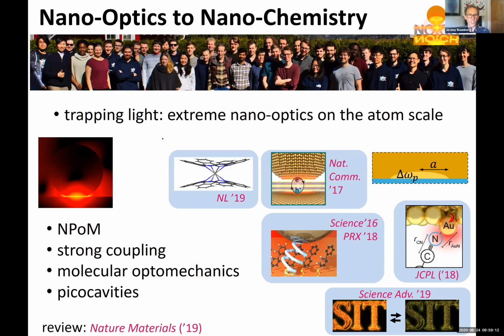So what I hope I've given you in this talk is, I hope you're now convinced that using this scheme, we can trap light incredibly tightly to the region of certainly tens of nanometer cubes and below. But also that we can couple these to anything that's in the gap. So as long as the dipoles are vertical, then we can actually get strong coupling in the system. We don't understand a lot about it, but we can see even more that when we pull individual gold atoms out of the facet, we can get this very strong additional electromagnetic field enhancement, and that allows us to do optomechanics in the system, some sort of strange molecular optomechanics. And you can even take this into the application space as well as looking at sensors.